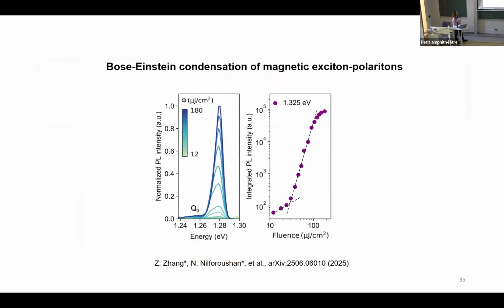Just a little advertisement. CrSBr is really an interesting material. I was constantly talking about this anisotropic dielectric function, but actually the dielectric function in CrSBr is so high along the b direction that the material itself acts like a cavity. When the photon goes in, it is trapped inside. And we have a hybridization of cavity modes with excitonic modes. So we end up having exciton polaritons. In another project in my postdoc, we could actually show that when we pump resonantly in some excitonic state, we can initiate the generation of Bose-Einstein condensation of exciton polaritons in a bulk of chromium sulfide bromide. This is the arXiv preprint in case you are interested in.